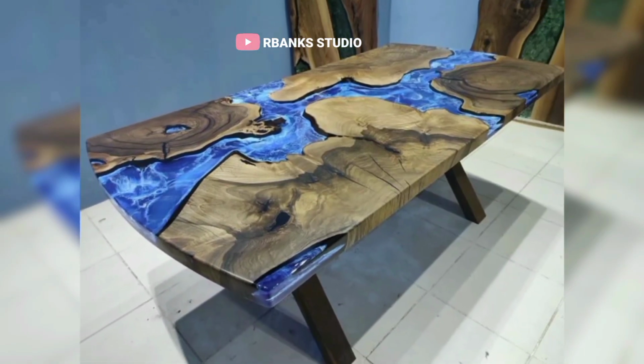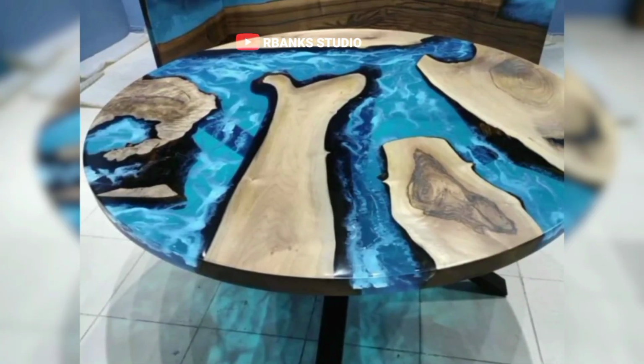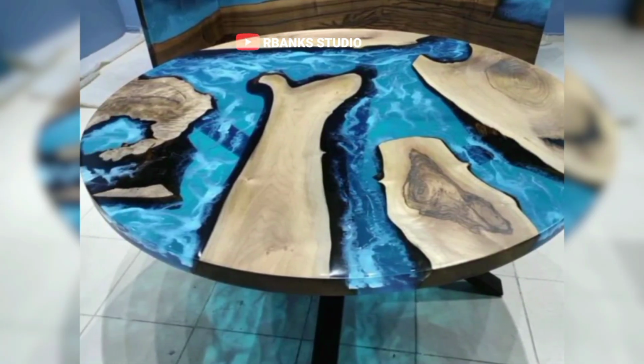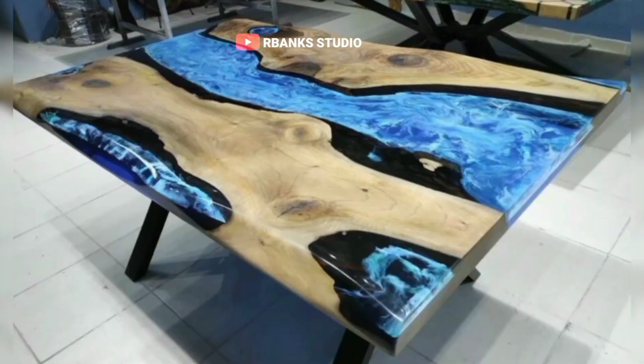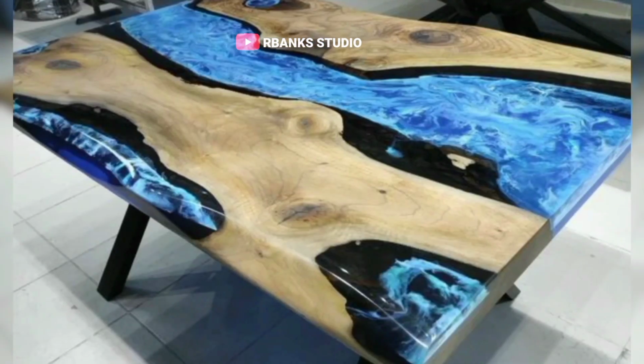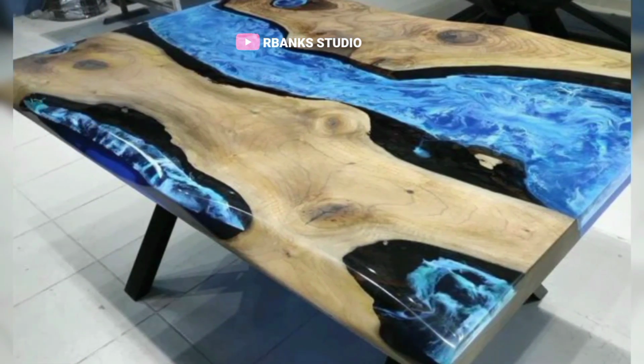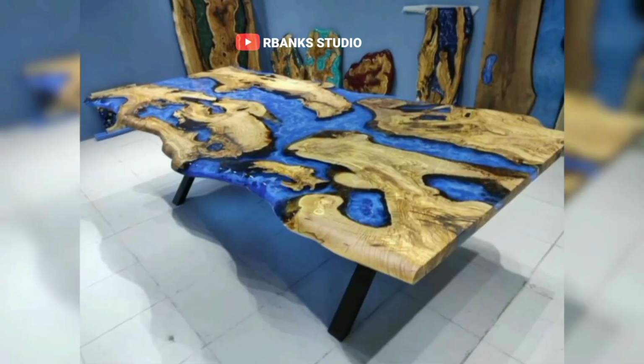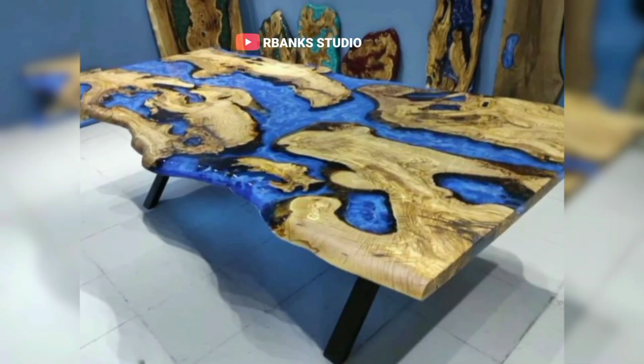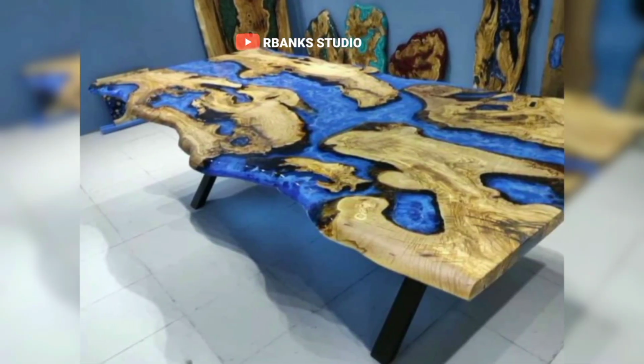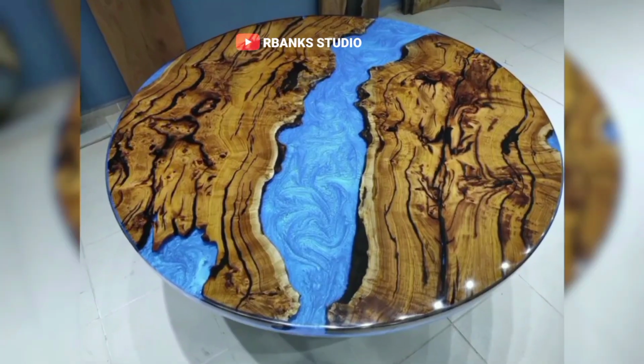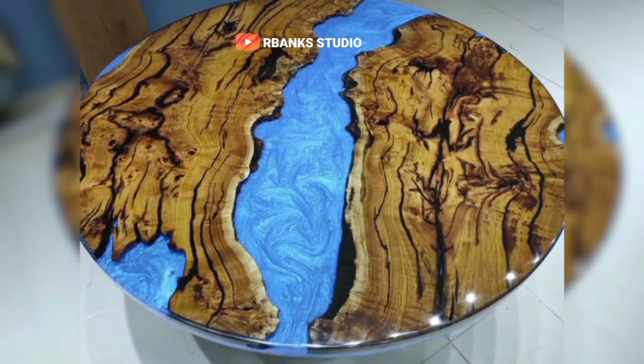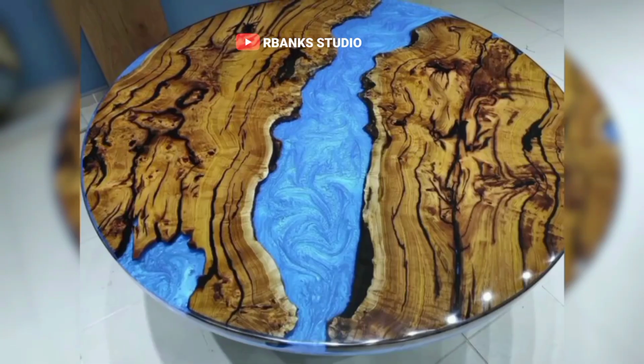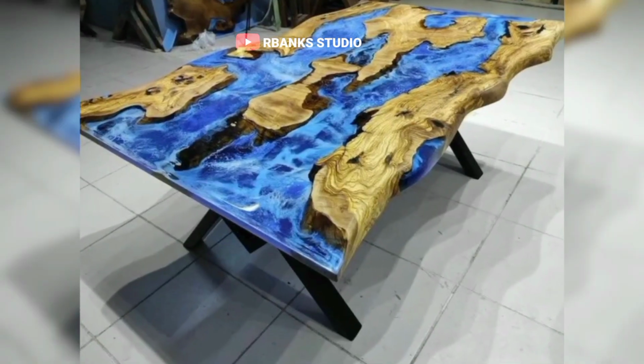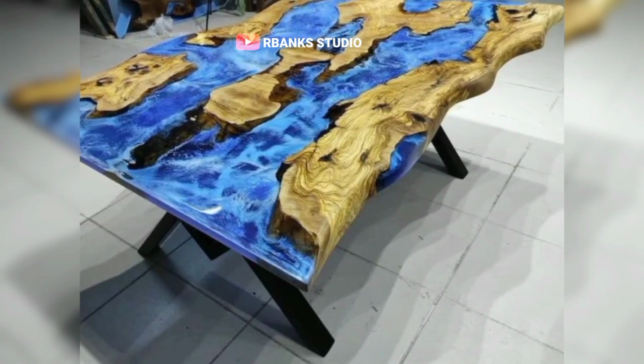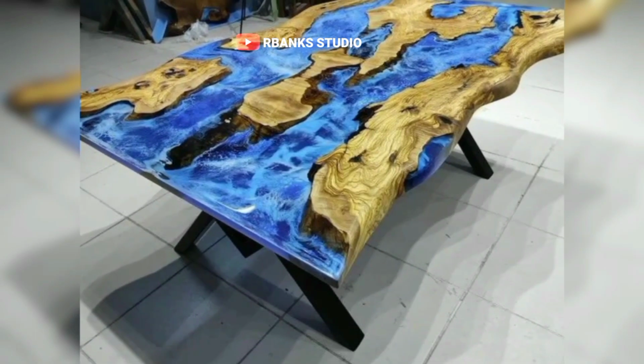What do you do after sanding? After sanding, I clean the area again and apply a small amount of epoxy resin to fill in the scratch. I use a fine brush or a toothpick to carefully apply the resin, making sure it's level with the surrounding surface. Once the resin cures, I sand it lightly and apply a final coat of polyurethane to restore the glossy finish. John, can you share some long-term preventive measures to keep epoxy tables looking their best?